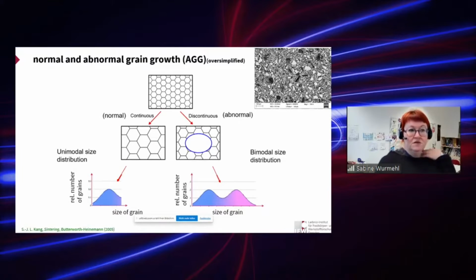It's also reported for different systems: if you undergo not normal grain growth, so continuous grain growth, where you have a unimodal size distribution of grains, but if you have a discontinuous, so-called abnormal grain growth, where you get at least a bimodal size distribution, or typically even a multimodal size distribution of grains inside your material.